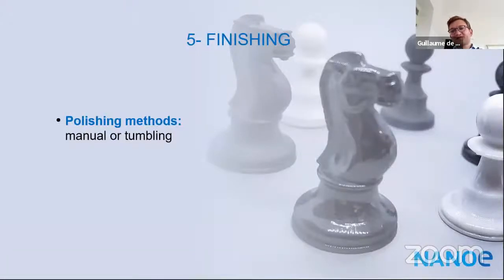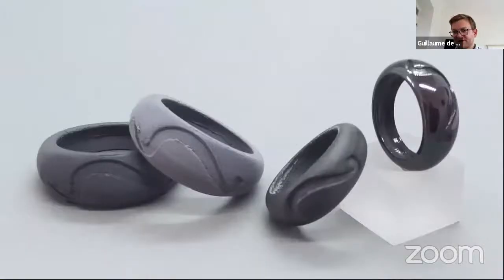Once you've sintered the part, especially if you're making a ring, you may want to finish it, to have a nice surface finish. This can be done manually. There's a lot of manual methods for polishing. You can do it with a few rotating tools. And one of the most effective ways to do that is tumbling. You basically put the parts in a tumbler with some polishing media, and you just let it turn for quite a long time, and this will give you some nice polished parts afterwards. Here are again the same parts after tumbling.